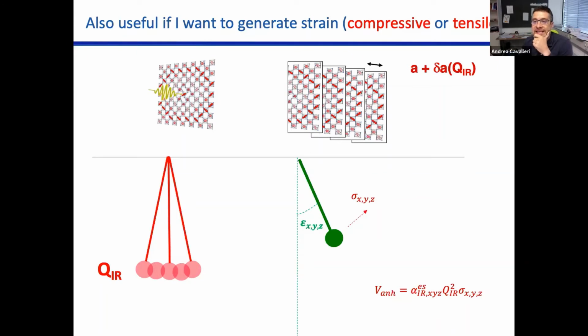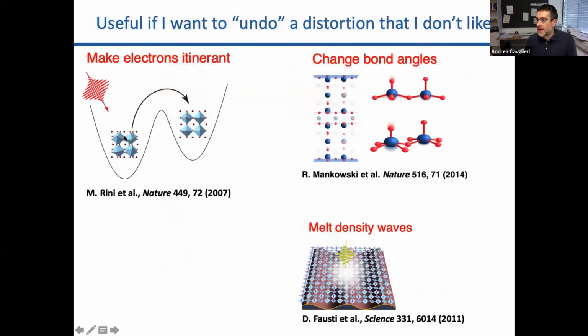So anonymous attendee, for M. Rini et al., you said that the bond angles can be straightened by an incident laser pulse. How can this be done? So the point is that I excite a vibrational mode which couples to a symmetric mode of total symmetry, a totally symmetric mode, which straightens these bonds. And there's a particular type of Ag mode that maps this structure onto this structure, thereby not reducing the symmetry, but raising the symmetry. I hope this answered the question.